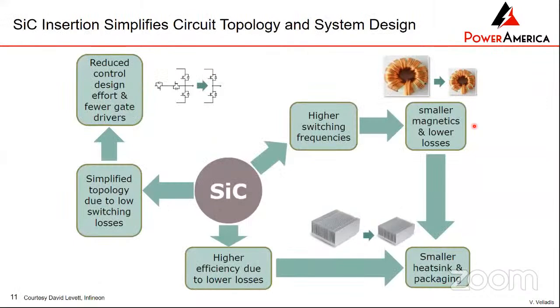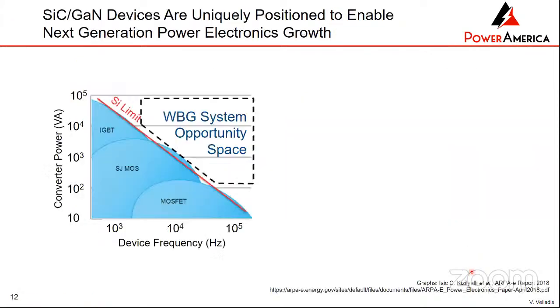Okay, so what is the advantage of using silicon carbide? Because you're able to do higher frequency and you're able to go to higher voltages, that simplifies the design of the circuit. So you have fewer levels if you're doing silicon carbide work. And because you're going to higher frequency operation, you reduce the magnetics. Instead of having large magnetics, you have much smaller magnetics. And of course, because silicon carbide has very high thermal conductivity, you're able to make a smaller heat sink and reduce the packaging. So those are the advantages of silicon carbide compared to the dominant silicon technology.